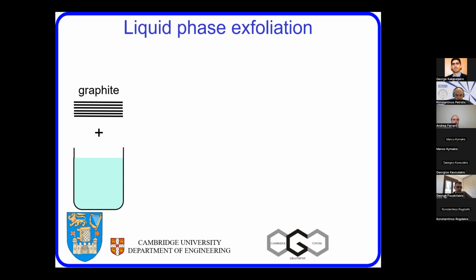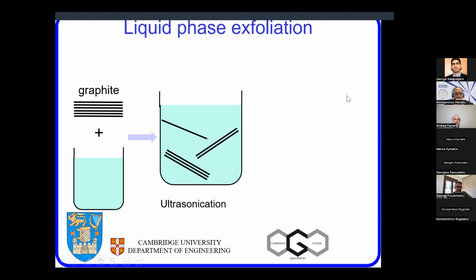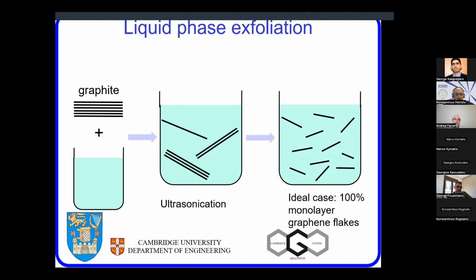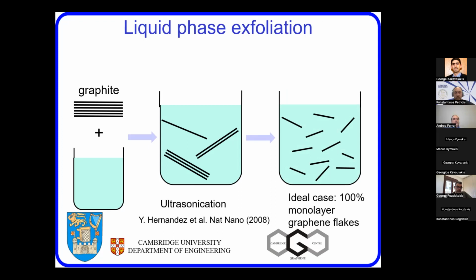So Cambridge and Trinity College came together, and in 2008 we proposed a simple system to exfoliate graphite, which was to take it, throw it in some beaker with some solution, some water or something else, sonicate, and ideally get 100% monolayer graphene flakes. In reality, what we got in 2008 was 0.8%. So it was a very small yield, but it was still bigger than 0. And so this paper was published. Yenny Hernandez was a PhD student at the time. Now she's a full professor. And strangely enough, the title is high yield production or something, but the yield was extremely small.